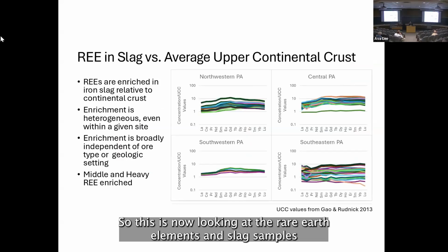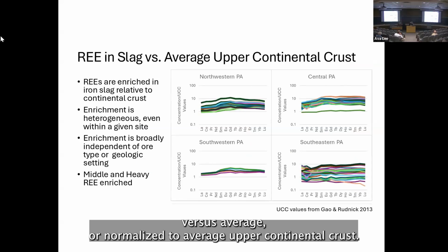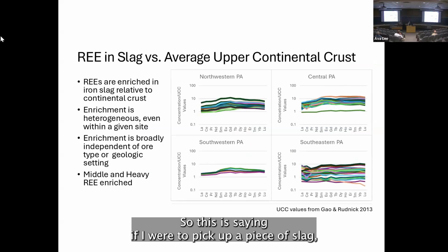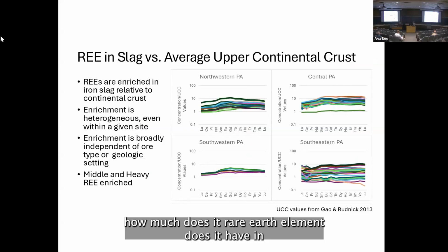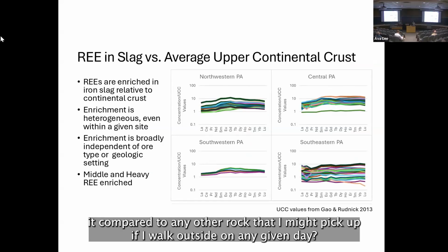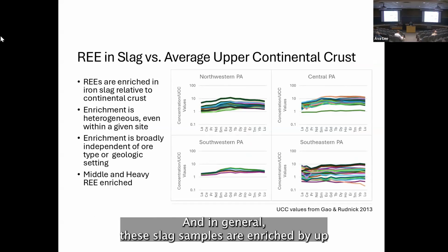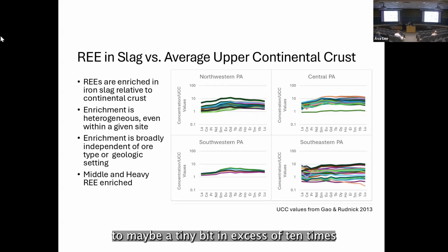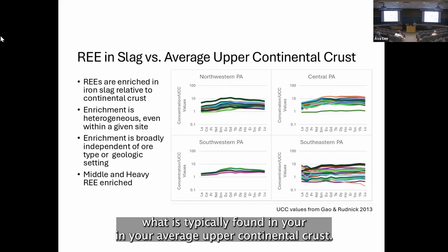So this is now looking at the rare earth elements in slag samples normalized to average upper continental crust. So this is saying if I were to pick up a piece of slag, how much rare earth element does it have in it compared to any other rock that I might pick up if I walk outside on any given day. And in general, these slag samples are enriched by up to maybe a tiny bit in excess of 10 times what is typically found in your average upper continental crust.